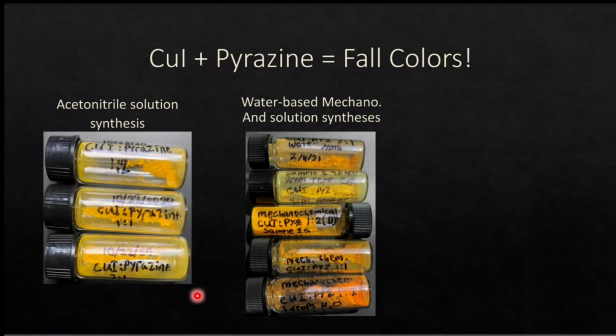synthesis. And we also tried to do a solution-ish synthesis in which we just dispersed the copper iodide into the water while it was reacting. And we got some interesting results. We didn't get very much crystallinity, but we did see much more variation in the color of the compounds produced. And so this made us think maybe something interesting was going on here.